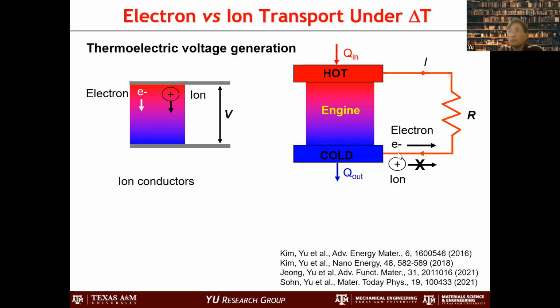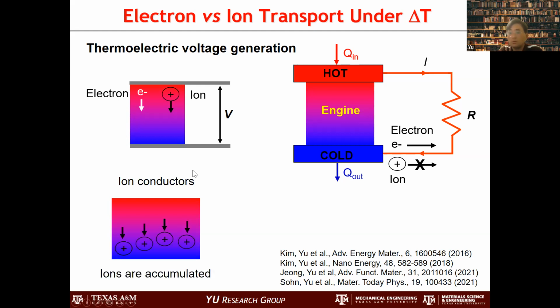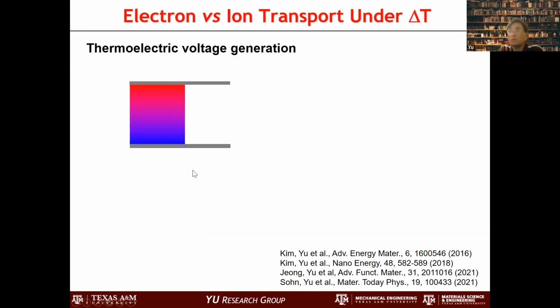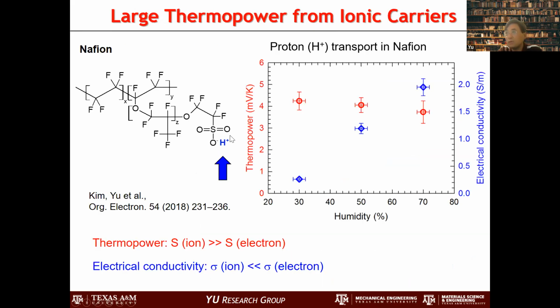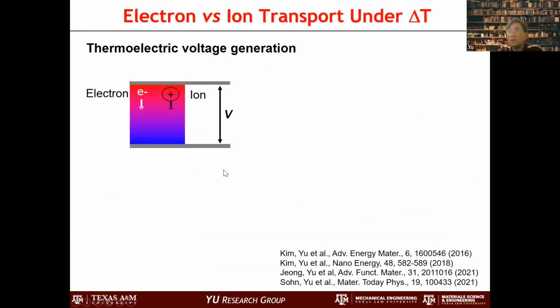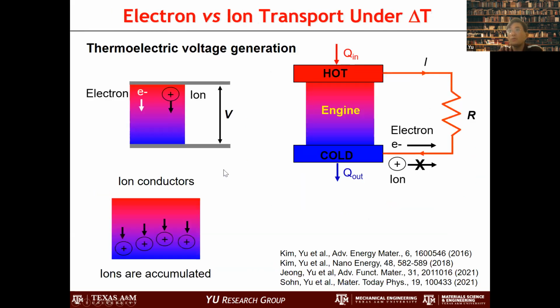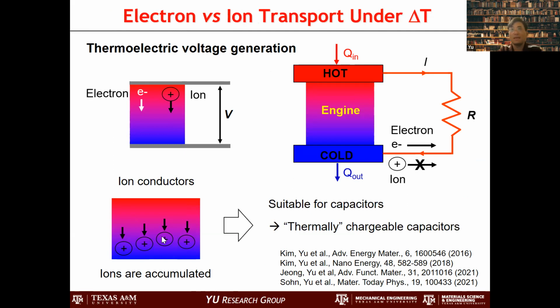So in this case, what we are using here is basically the ion. Previously, as you saw, this material basically uses ions, here a proton, instead of using electrons as in conventional thermoelectrics. So in this case, we basically accumulate the ions on the cold side, and since the ions cannot get out, we basically use this as a capacitor. And so that's what we did.